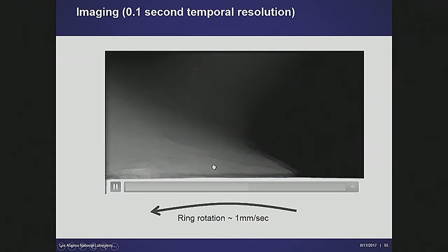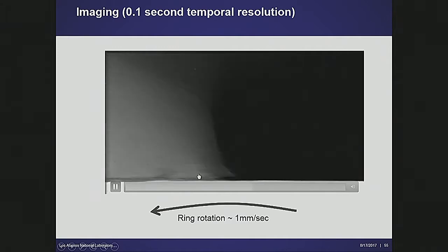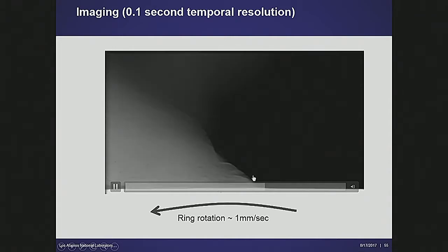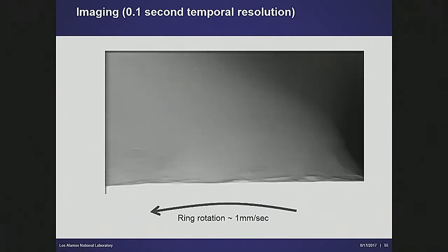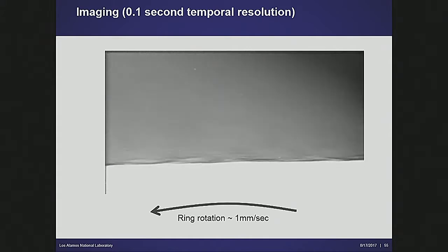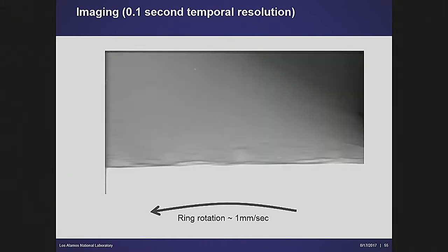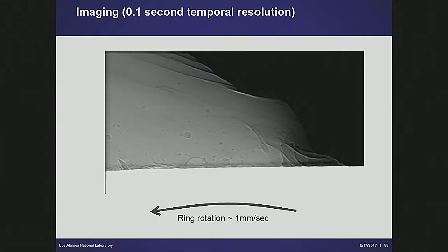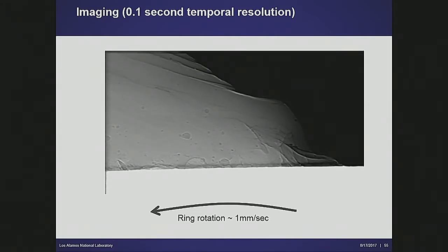Where I'm looking right now is just on the top of the wheel, and this is the leading edge of the weld with a 1/10 of a second resolution, right? It's not quite good enough to give us what we want yet. Now if you watch it just at the end, you'll see they're moving the field of view. This white line was the wheel itself coming up into the field of view. It stopped, we turned it off.